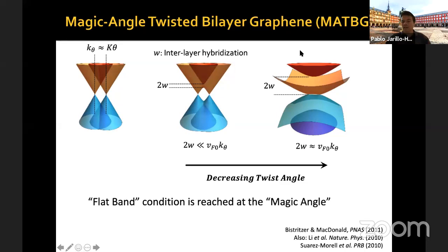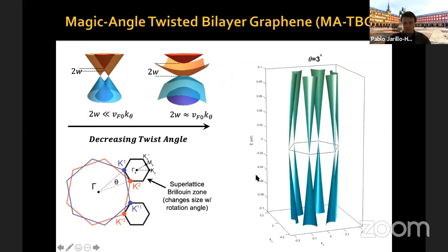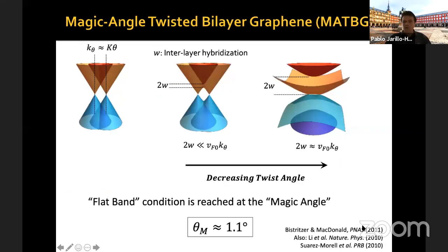This flat band condition is reached for an angle of rotation which depends on which two materials you put on top of each other. But for the case of graphene, it was coined by Bistritzer and MacDonald as the magic angle, and it happens to be about 1.1 degrees. I should mention that there were very interesting experiments about the same time, a little bit earlier, by the group of Ivan Brihuega, demonstrating a signature in STM spectroscopy, a van Hove singularity that moves towards zero energy at about this angle, 1.1 degrees. There was also earlier work by Suárez Morell predicting that there would be flat bands at small angles in twisted bilayer graphene.